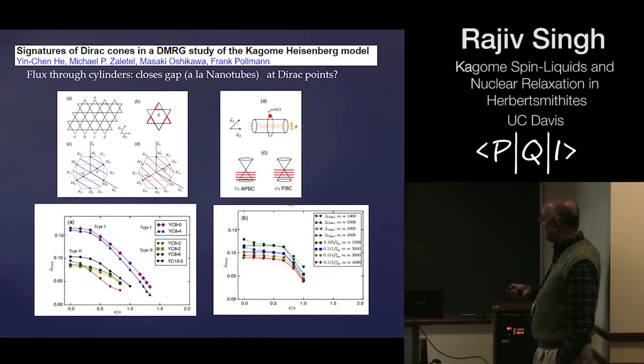So their idea was that what one wants to do is, rather than having the normal folding of the cylinder, we can try folding this A point, let us say, to over here or over here, we can put a twist there. First of all, that can change the lines that are allowed for the system, or we can put a flux through this system, and the flux means that in the transverse direction you can add an additional phase factor, and if it is a Dirac spin liquid, either of these things should end up closing the gap. Now, as you can see in their data, this is the data over here, applying these things, causing different kinds of boundaries as well as applying this does reduce their gap, but it does not quite close it to 0, and in fact at the end they argue that the DMRG method should break down by the time you end up close to this